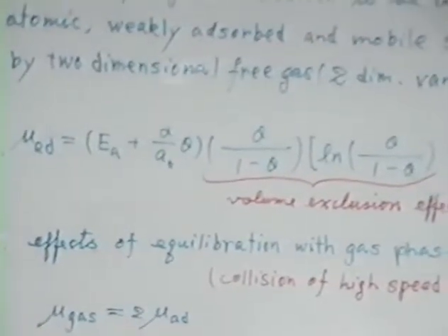Skipping over the derivation, we can obtain this very elementary equation, perhaps you may remember easily, the chemical potential of the adsorbed hydrogen in the two-dimensional fluid. We obtain this equation. Here I want to emphasize that the coverage theta appears in this form and this form. In the Langmuir isotherm case, of course, we obtain only this part. So with increasing the coverage, the chemical potential of adsorbed hydrogen becomes rapidly high. That means the coverage might always be small.